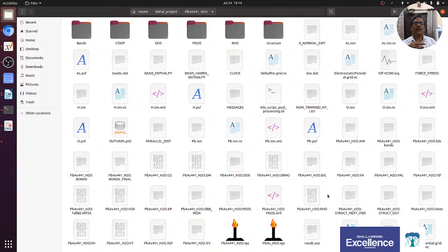And then I have optimized this water molecule, and then I have linked this water molecule with that planar structure and optimized the complete system. And now I have created that raw file for each category, each system: one for the composite, second for the host, and next one for the molecule. And now next I will try to generate that cube file.